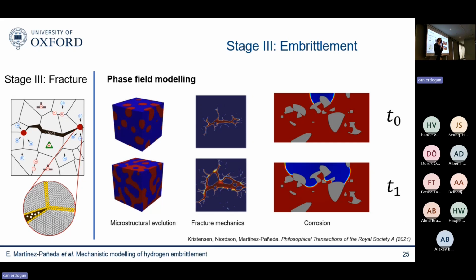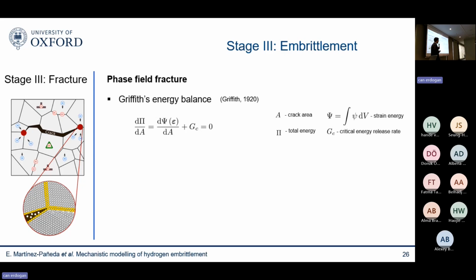And I think, again, going back to what I said before, the two aspects that are challenging in this problem is first, mathematically, it's difficult to predict cracks. And now it seems that we have a tool that finally allows us to do so. But the other one is that the method has to be physically sound. These nice colors need to correspond to reality. And I think the phase field is a nice platform for that because it basically allows you to incorporate Griffith's energy balance. So this goes back to the foundation of fracture mechanics, thermodynamics of fracture. For a crack to grow, the energy stored in the material has to be equal or larger than the energy required to create new surfaces, the fracture energy, the critical energy release rate.